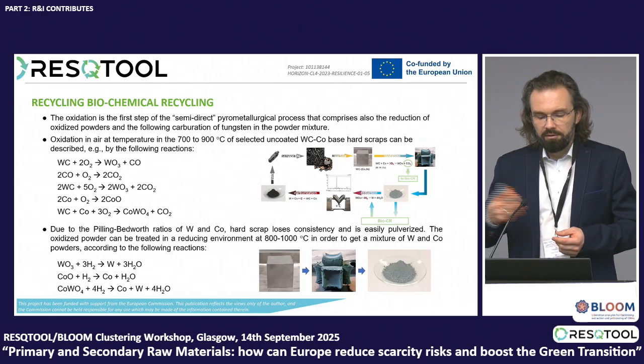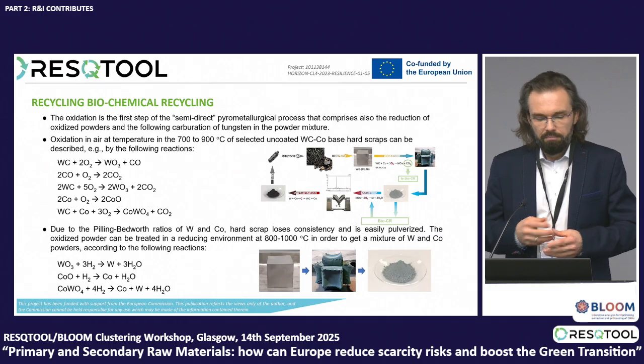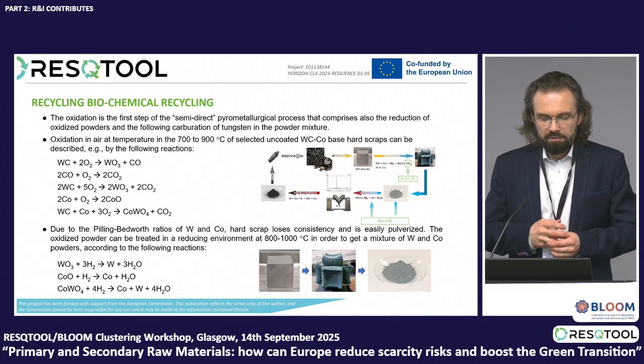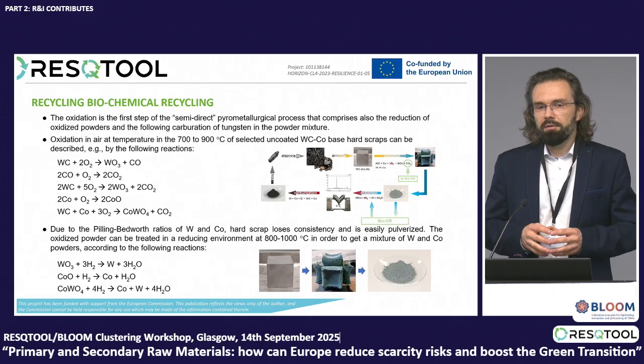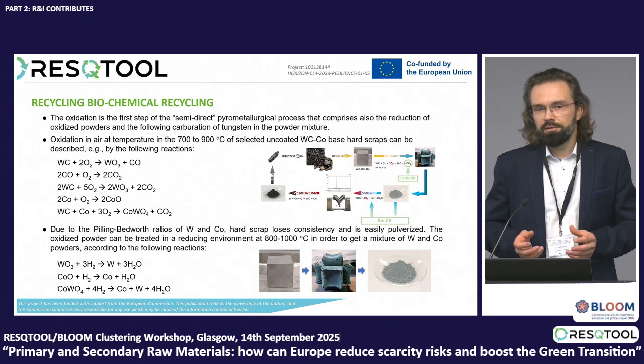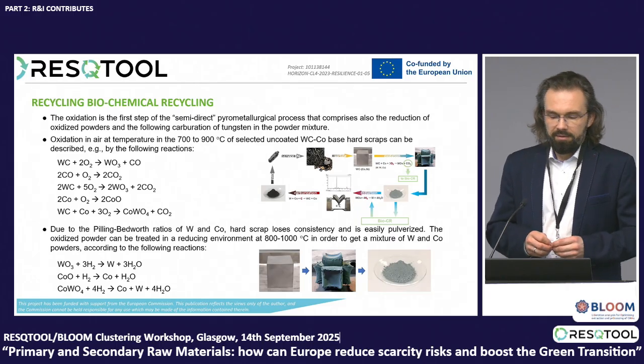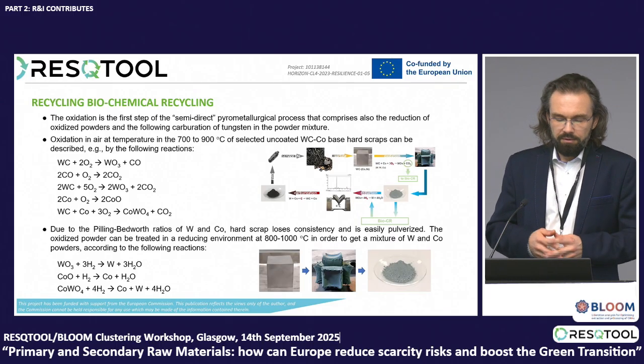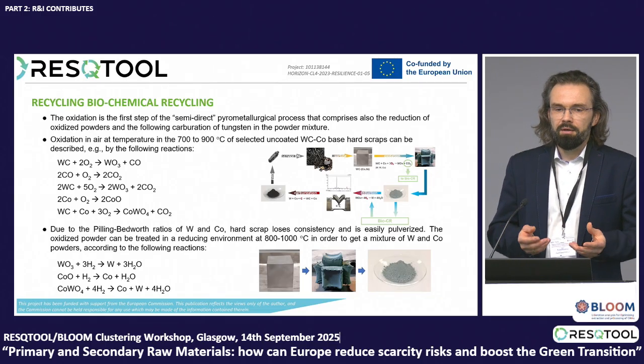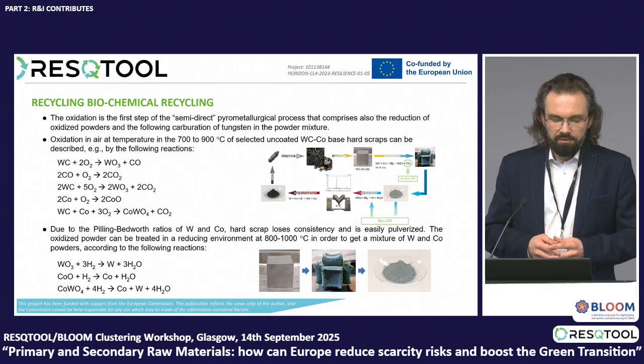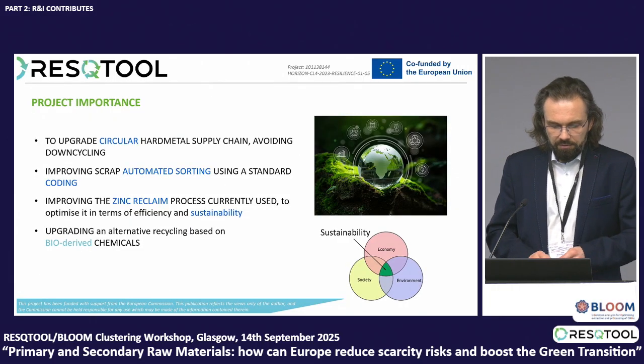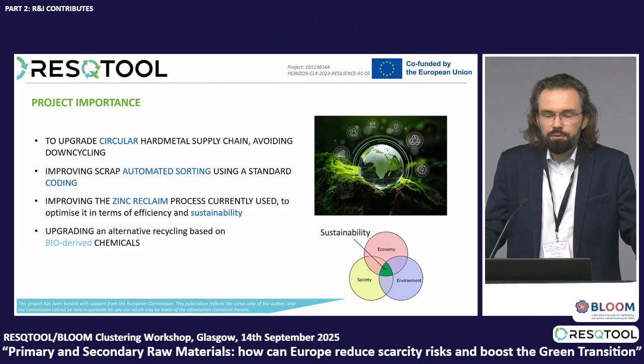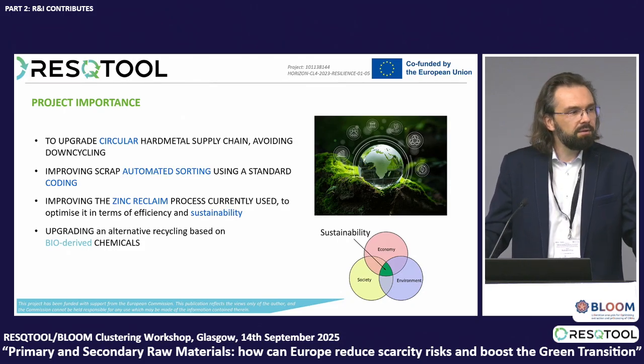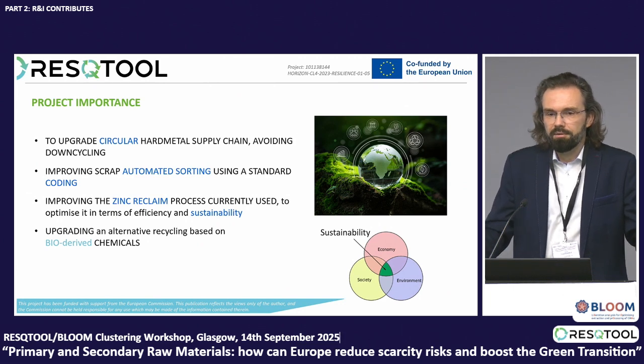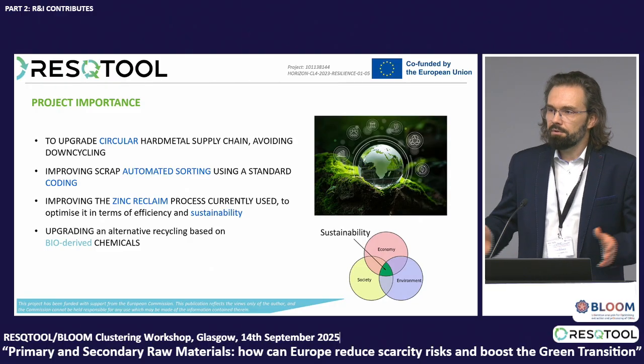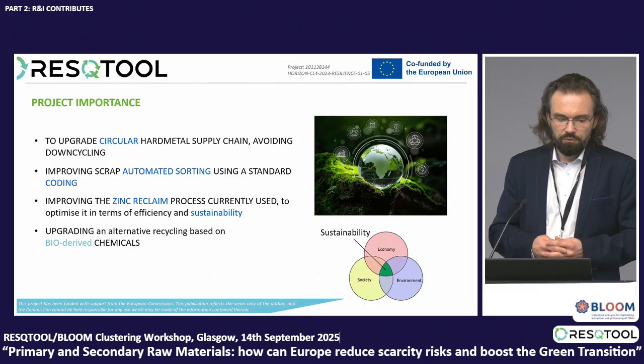Then we can recycle the hard metal scraps by biochemical recycling. One of the partners is developing this method, and it's based on the use of biochemicals, which are not like hydrofluoric acid or other acids. They are based on much more environmentally friendly ways to recover the materials in a good form from the very mixed scraps, which cannot go to the dedicated recycling. Then after that, we are reusing the powders acquired from the recycling, and we are making new tools to verify their robustness, the quality, and the lifetime. So this is the full cycle from recycling to manufacturing of the new tools.